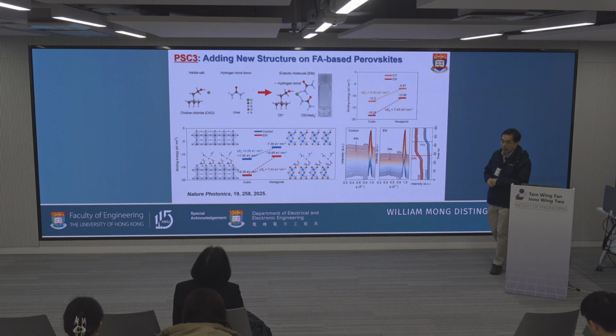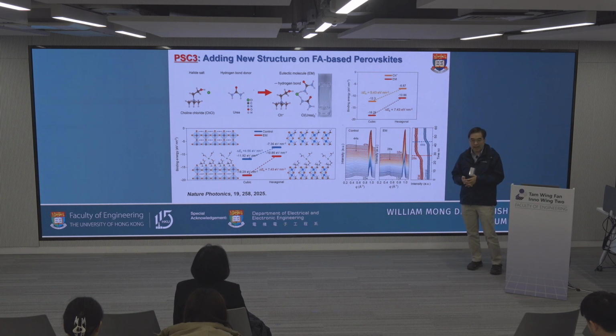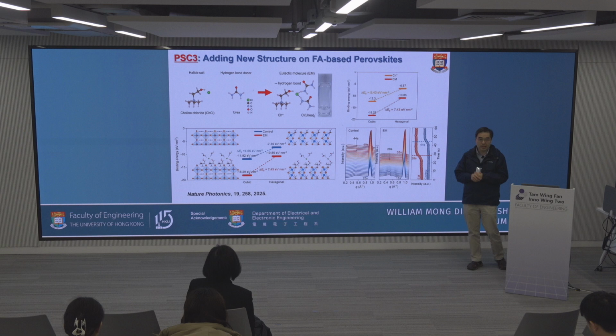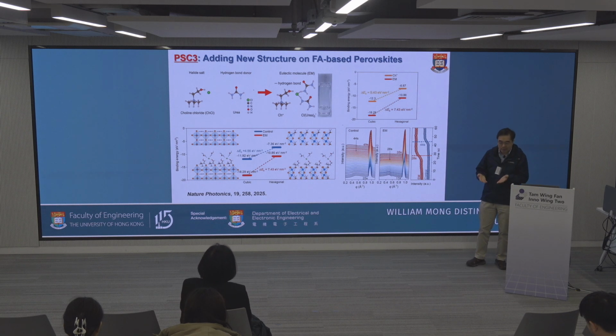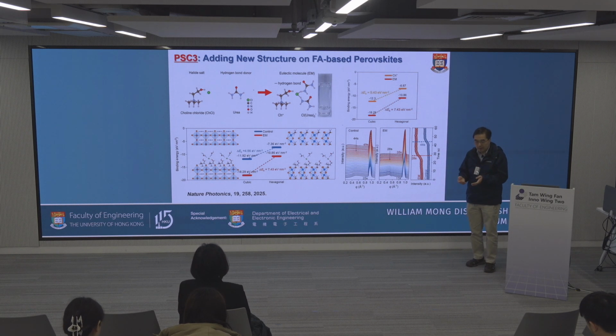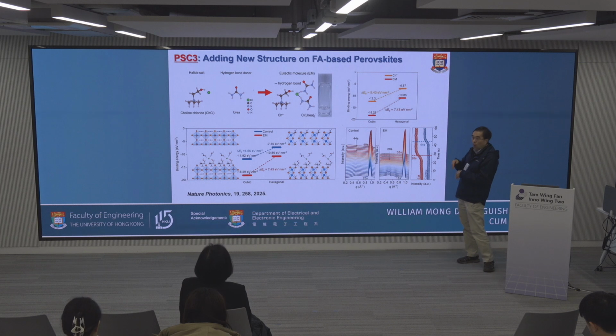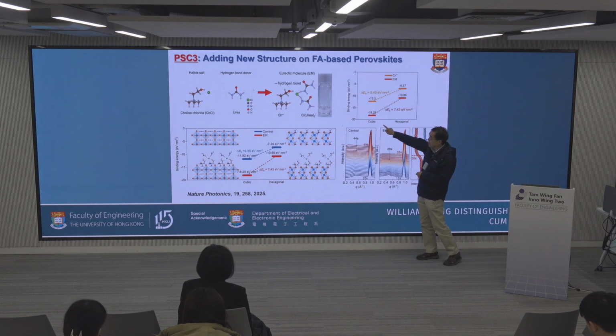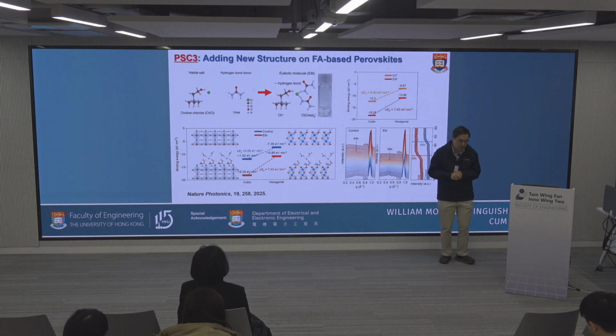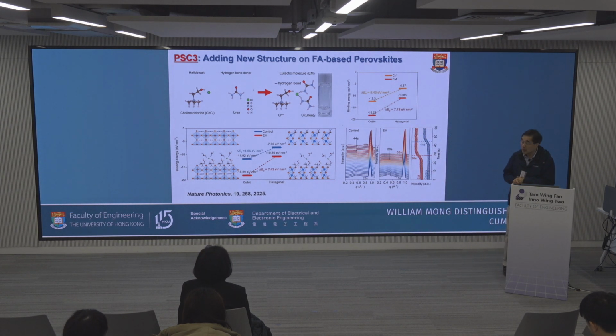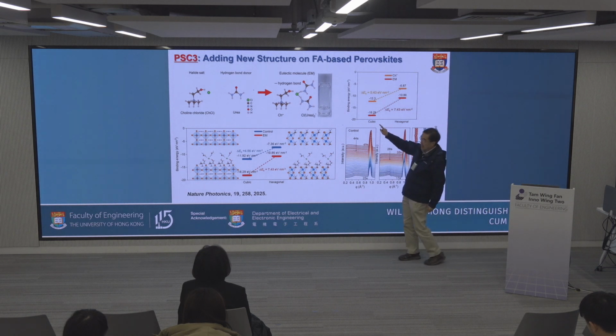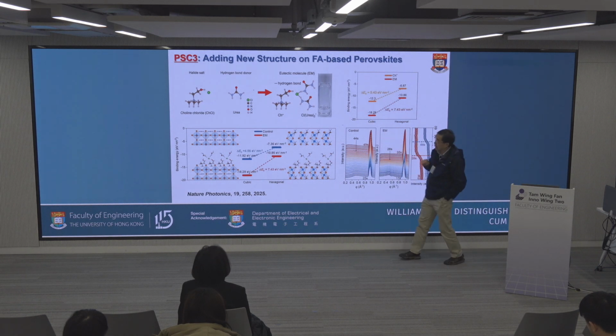Next, we know the perovskite, we address the boundary, we address the surface. Another issue is that because we're using a solution process, it's hard for us to maintain the cubic structure all the way when we form the perovskite. Because of the solution process, we cannot do it absolutely. So we always have cubic and hexagonal structures forming at the same time. But we know that the photo-absorbing material is the cubic perovskite.